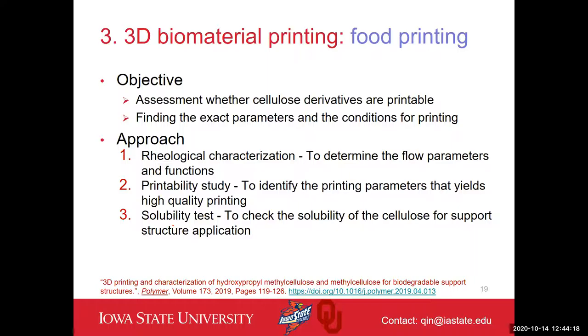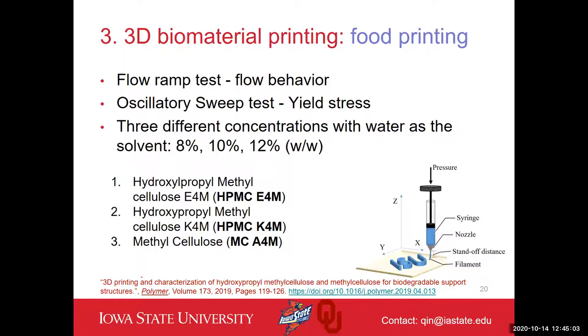We want to optimize the printing parameters so that we can achieve stable printing using this type of new material. The approach that we are using is very standard. We first characterize the rheology property of the material in liquid phase, and then investigate how temperature affects the rheology property. We run a printability study to identify the optimized parameters for printing, and we use a solubility test to see if this is a good replacement for supporting structure in 3D printing. The article below is the first article we published that relates to biomaterial printing in our group. In that study, we also use extrusion-based 3D printing to extrude the cellulose material.